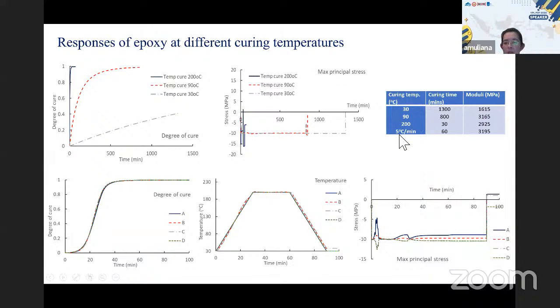So now one way, what if we do a slow heating? With slow heating, you look at the cure time, 60 minutes is not too bad, and we have a properly cured sample with relatively high modulus. So when you look at the slow heating, it's more uniform curing when you see all this degree of curing at different locations, right? So with more uniform curing, we minimize the effect of this residual. As you can see, we see some changes in the stress, and they're all fluctuating very close to the 10 megapascal pressure that we prescribe. At the end, the residual stress is actually very small, minimal, compared to the previous example that I gave you, right? So all of this has a consequence on the material response.